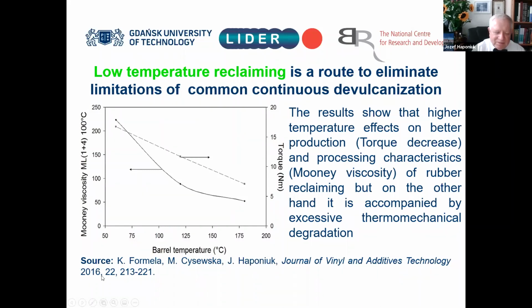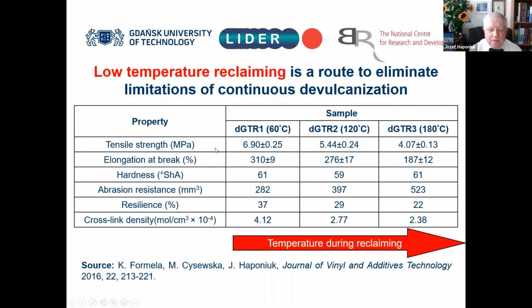It is an example of previous works showing characteristic of low temperature reclaiming, but 4-5 years ago we had still higher excessive thermo-mechanical degradation, which was improved at present at these products and these experiments which are performed nowadays. So comparing of properties showing us that at higher temperatures, the most important tensile strength and elongation at break, abrasion resistance will be lowered, so the quality will be lower as well.